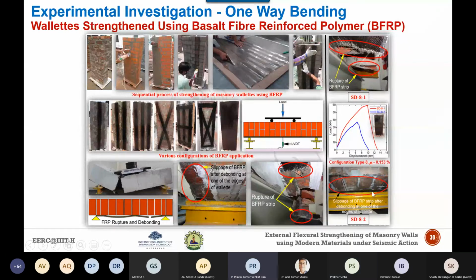Now, in addition, in a few cases, there is a combined failure mode. In one case, there is a rupture, and in the second case, there is basically a debonding. And you can see that when there is a debonding, the full tensile strength of the material is not utilized. And therefore, in this case, you can see that the specimen with the debonding mode got a strength of around 30 kilonewton, and when the specimen basically failed in rupture, where the full tensile strength of the material has been utilized, the strength has almost gone to double, almost reaching 60 kilonewtons. So this FRP strengthening technique also shown a significant enhancement.